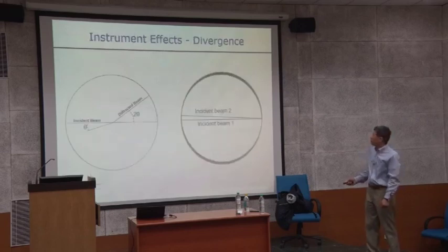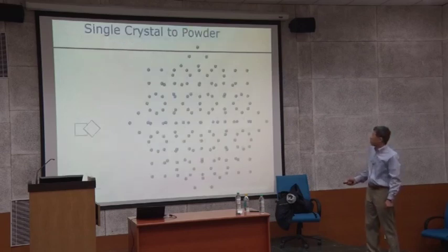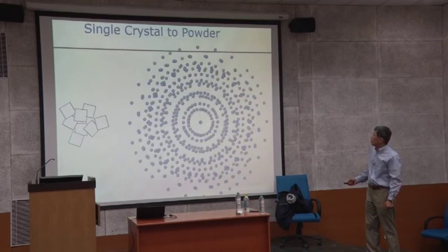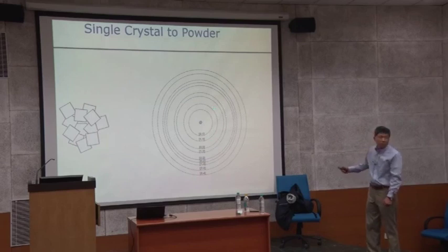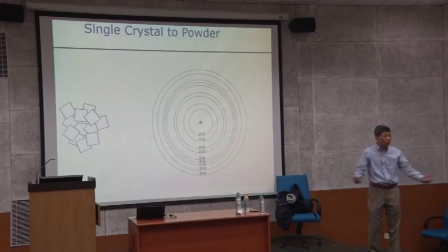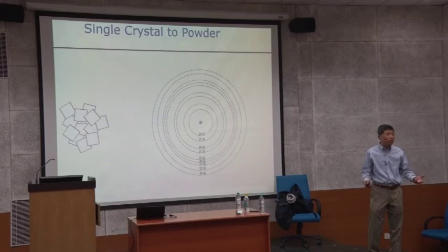But in powder diffraction you can see all these things. So you can actually have this one is 100, this one 110, 111. You have all of this possible. We can access all. With powder diffraction you don't need to move your sample, only theta to theta is enough.